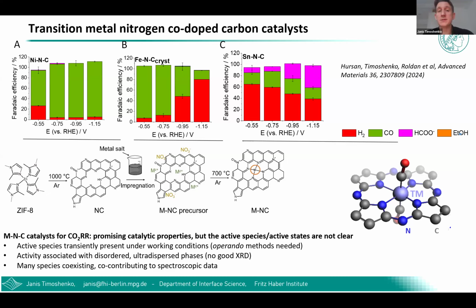And if you run this CO2 electroreduction with this catalyst using these different transition metals, you can get different reaction products. You can get more CO for nickel, more hydrogen for iron-based catalyst, or if you use tin-based catalyst, you can get even some formate. In particular, nickel-based nitrogen-doped carbon (Ni-N-C) catalysts are currently very actively studied in the context of CO2 electroreduction, because they can convert CO2 into CO with nearly 100% selectivity, which is very rare and quite nice from a technological perspective.